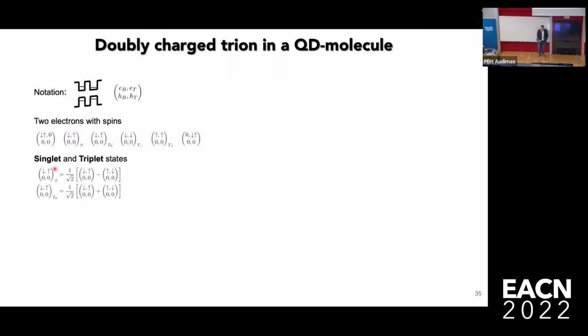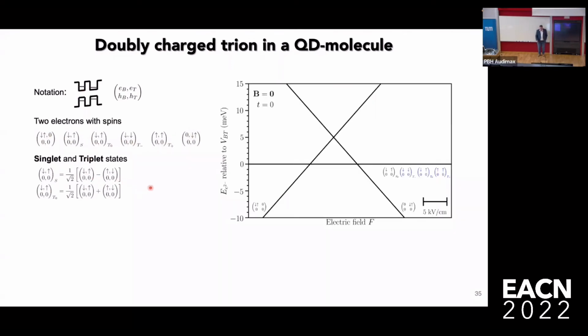The 2 electron states then form singlets and triplets, just as you'd expect, like the excited states of the helium atom. And if you then plot the energy diagram, fixing the energy at the triplet state, so there's the triplet state energy, these are the singlets which shift as a function of the electric field, and they should anticross when they couple together, and that produces there at this particular point in the field, a region where the triplet and the singlet have an energy gap which is independent of electric field, and it's also independent of magnetic field.